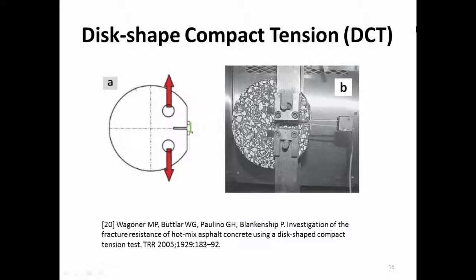Then we come up with the third one. Because of the wedging effect I stated for the SCB test, they said we don't want this wedge. We come up with these 2 holes, and we tear them apart and let this crack grow. Because of the similar cylindrical shapes, this one has also been adopted since 2005, and this is a very, very popular test right now.